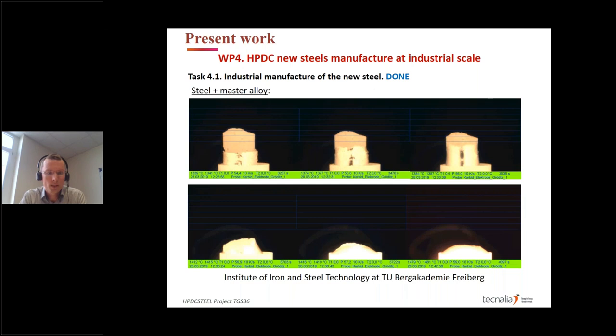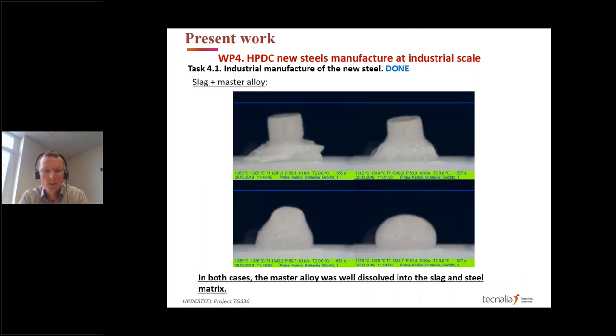Here you can see some results of steel and master alloy. On the top left picture, you see an alumina sample on the bottom. Then there is a steel sample of H11 grade, and on top, there is master alloy. We could prove that the master alloy melts at approximately 1480 degrees C, so there is a dissolution between master alloy and the steel sample. Further, we could also see the reactivity between the slag and the master alloy. We proved that in both cases the master alloy was well dissolved into the slag and into the steel matrix, which was very important for us to understand beforehand, so as not to expect any phase separation during master alloy feeding at the electroslag remelting process.